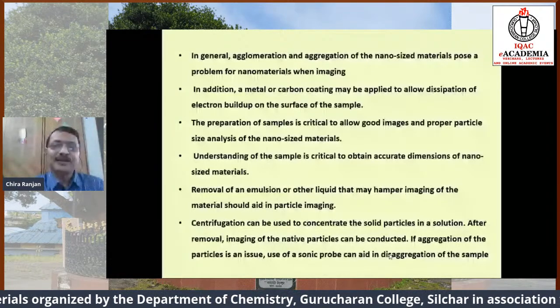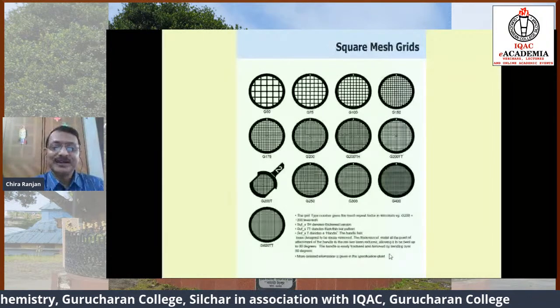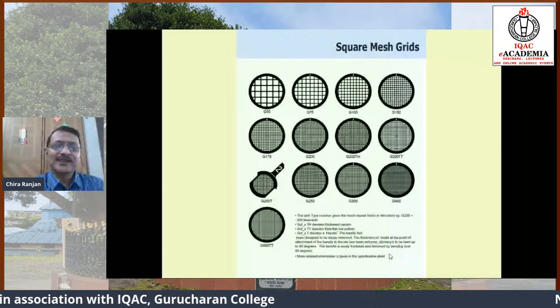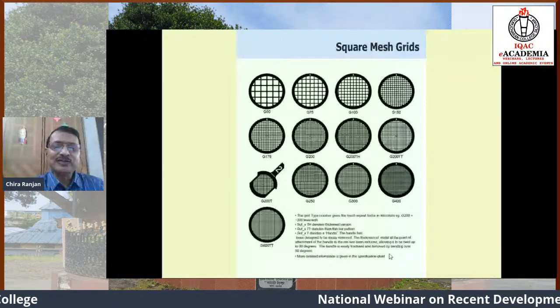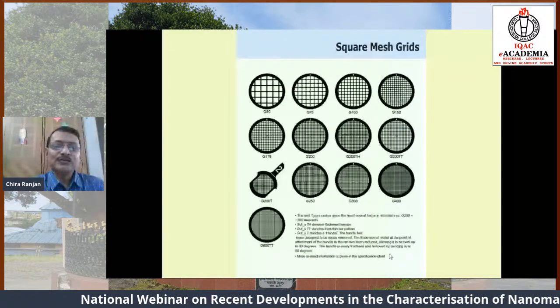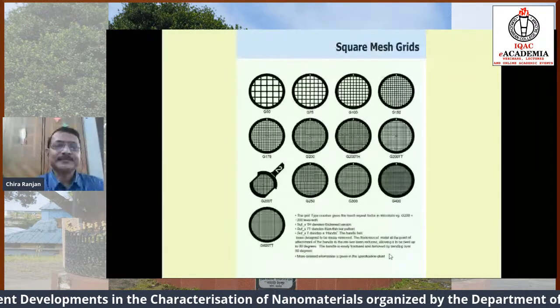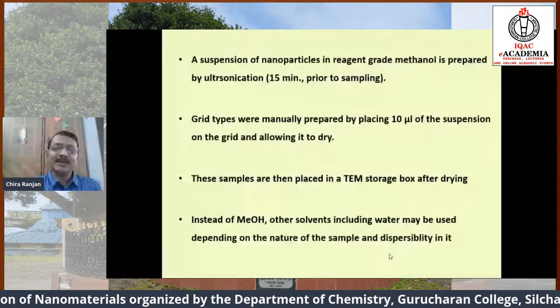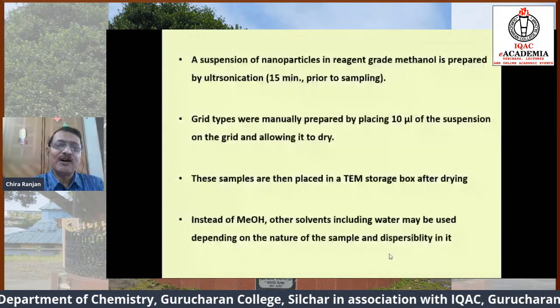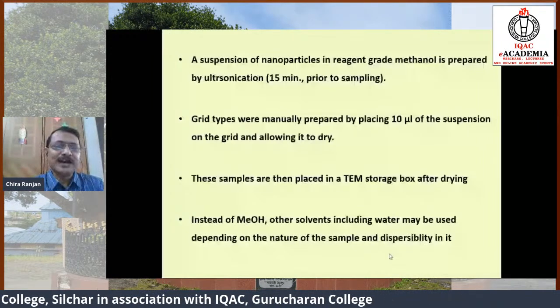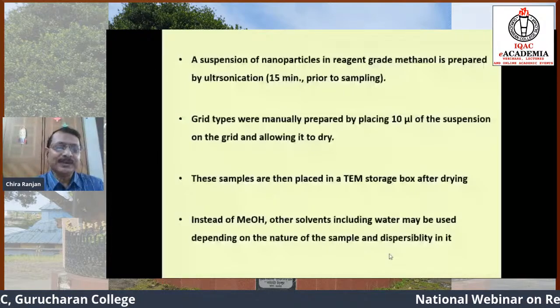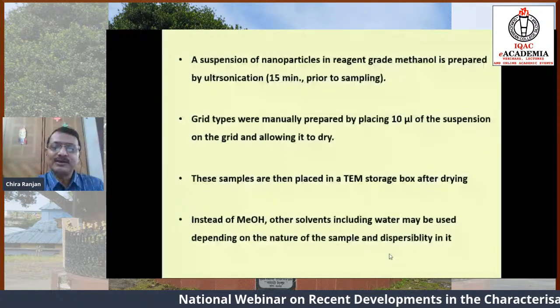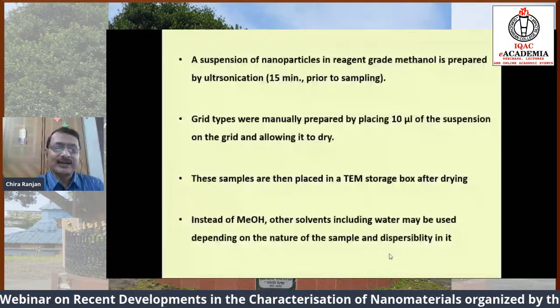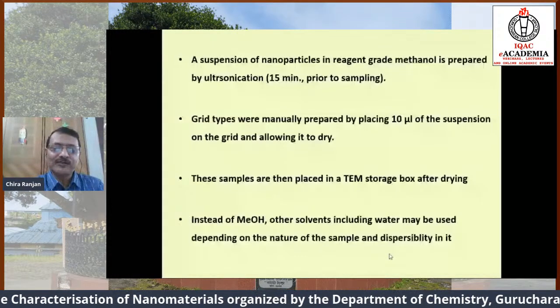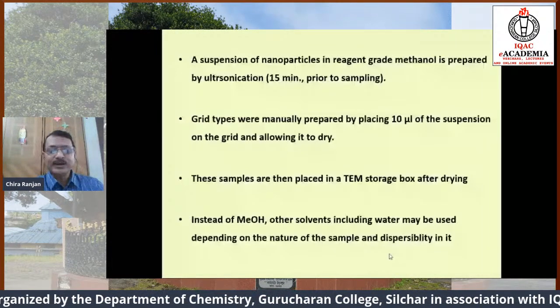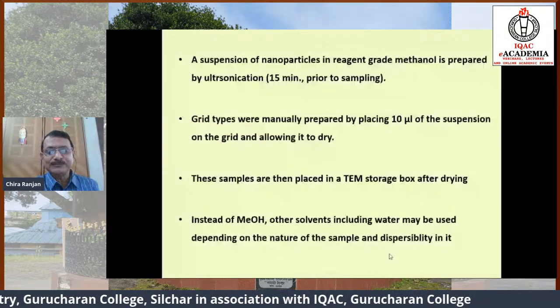Here are the images of different TEM grids having different mesh sizes. So if we have some prior idea of the nature of samples, we can actually make some planning to select the grid to be used for TEM. A suspension of nanoparticles in reagent grade methanol is considered most ideal for the preparation of samples by ultrasonication. Ultrasonication can be done for about 15 minutes prior to the sampling. Grids were manually prepared by placing 10 microliters of the suspension on the grid and allowing it to dry. These samples are then placed in a TEM storage box after drying. Instead of methanol, other solvents, including water, may be used depending on the nature of the samples and dispersibility in it.